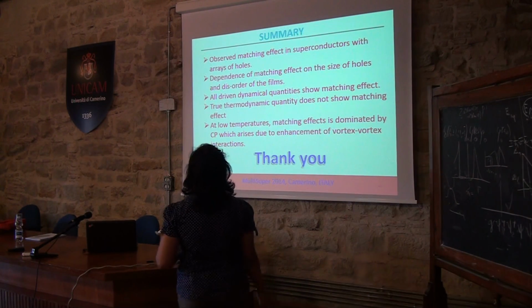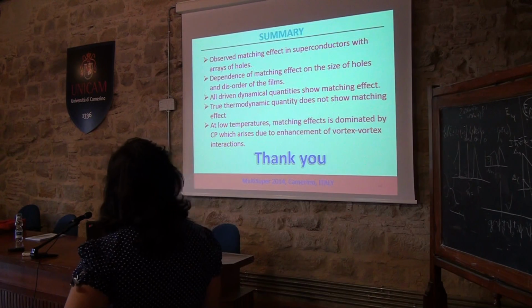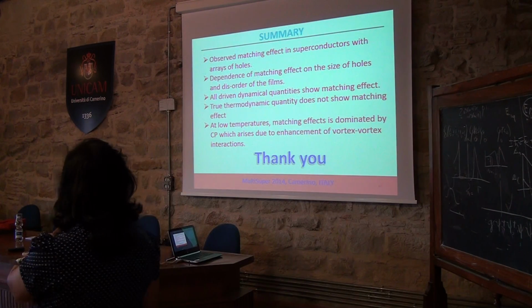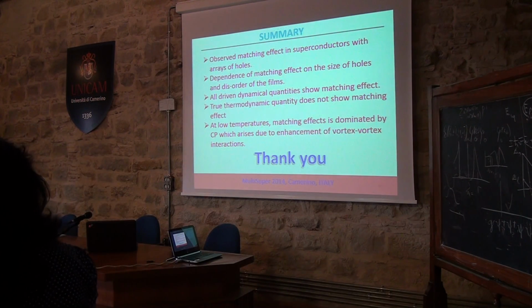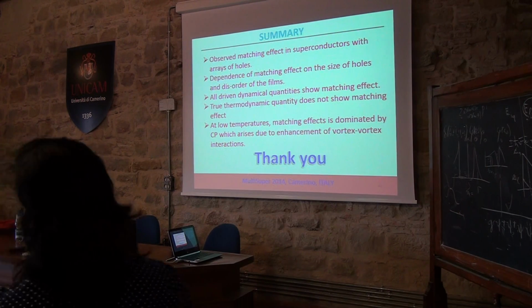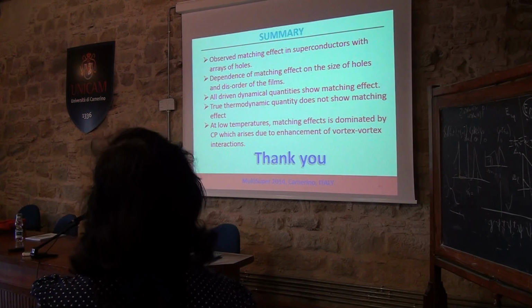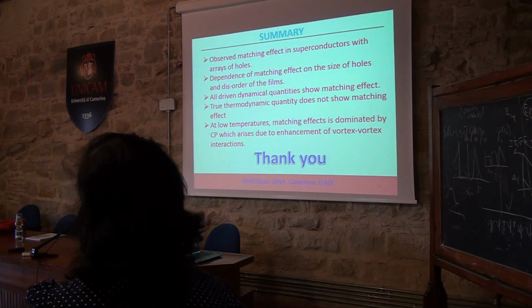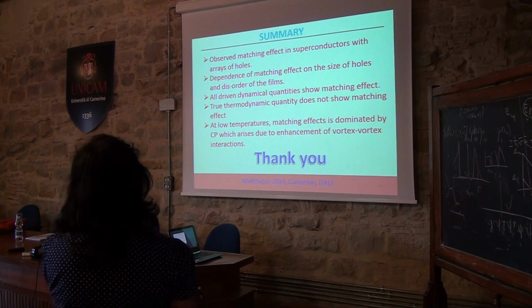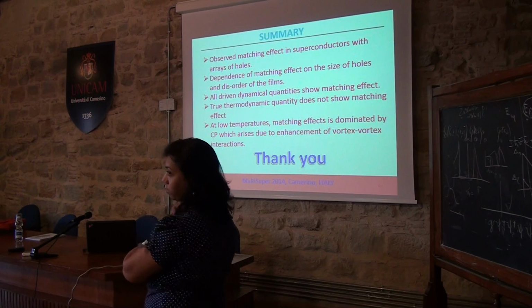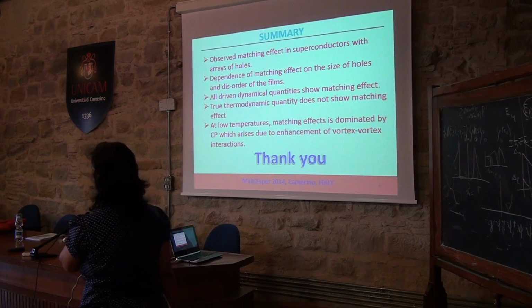So finally, the summary. We have observed matching effect in superconductors with an array of holes, and we have seen the dependence of matching effect both on the size of the holes and the disorder of the films. What we have seen is that all dynamical quantities show the matching effects, while true thermodynamic quantities are not showing the matching effects, which says that this is mainly dominated by commensurate pinning, which is due to the enhancement of the vortex-vortex interactions.